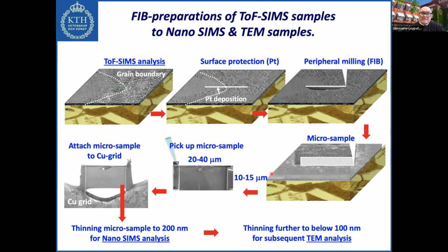And for doing this, we need to make quite an advanced surface preparation first. If we start with the sample which was used for time of flight SIMS, we saw it from up here. Here's the grain boundary. And now we want to look at the grain boundary region deeper into the material. So what we do is put a line of platinum for surface protection. This is platinum, which is deposited on the sample. And then by peripheral focused ion beam milling, as seen here, we can mill along the grain boundary, because the grain boundary is deeper inside here, and the milling does not take the platinum. Platinum protects from the FIB milling.